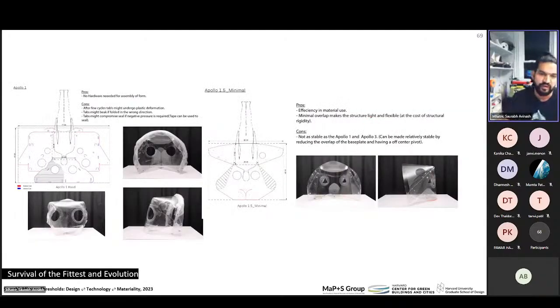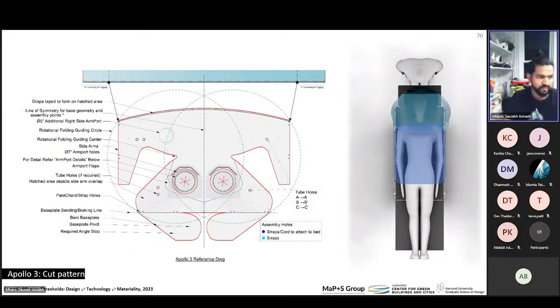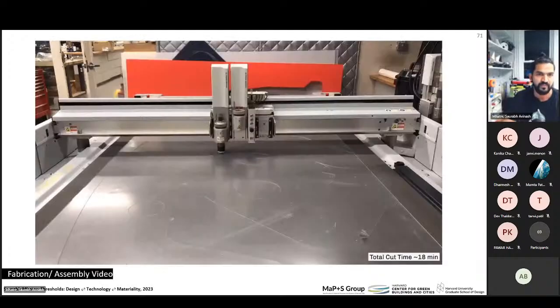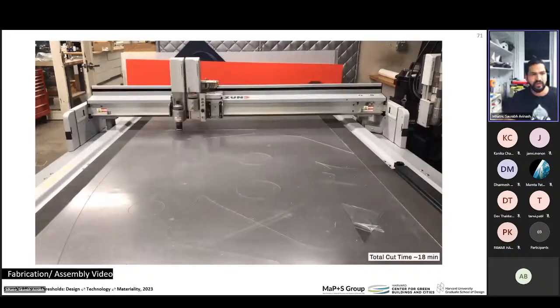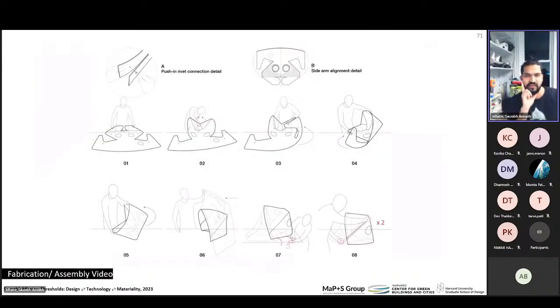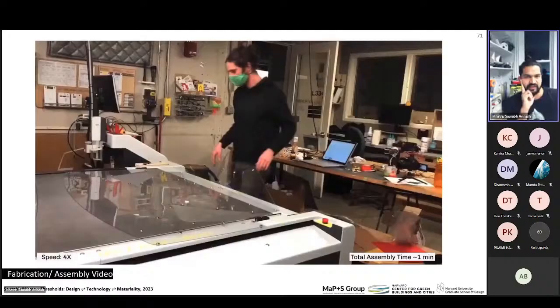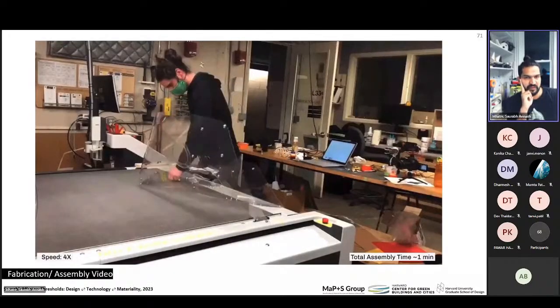Some of these stood out as viable options which satisfied most of the critical guidelines highlighted in the start. They did have some demerits though. Looking at the pros of the most promising options, we designed the final hood which had the best parts of the above options and none of the demerits. So we came to the final design, what we call the Apollo 3. This shows a quick video of the fabrication and assembly. It can be cut out of a thick PETG sheet in less than 20 minutes and assembled under 1 minute with minimal joinery.